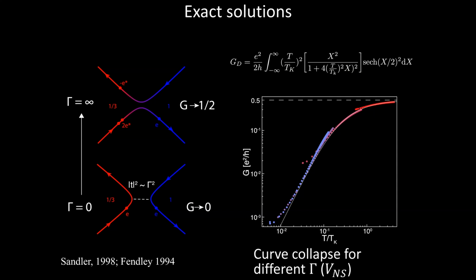But it turns out there's actually two sides to this problem. And actually this problem, because it's one of these quantum impurity problems, so-called, many of these were solved exactly by, I think this one was solved by Bethe ansatz in the early 90s. So you know a lot about this problem theoretically. And in fact, one way to think about this problem is that the universal regime is essentially where the junction between a nu equals a third and nu equals 1 wants to be disconnected, right? That's what this is telling you.